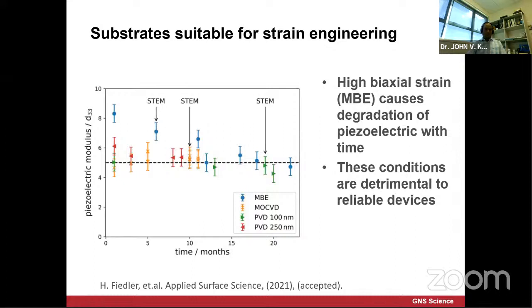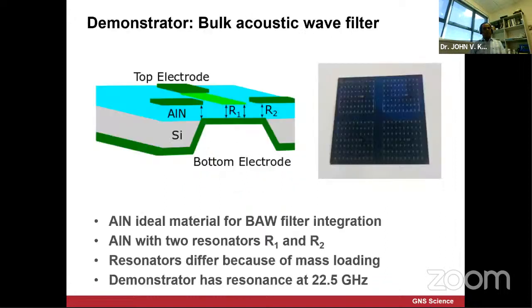So this is one of our recent results. Obviously, once we had filed the patent, we published that paper, which I showed you before, in APL and Acta Materialia. So what we did then is, all right, we got a demonstrator device. We made our own resonators, and you can see the schematic on the left-hand side. The right-hand side is a real device. It's made of implanted aluminum nitride, the strained material. Then we have two resonators. We are connecting them and looking at the frequency resonance up to 22.5 gigahertz.